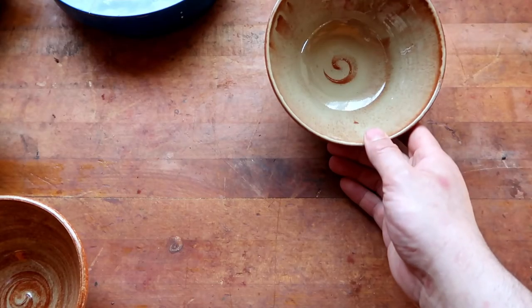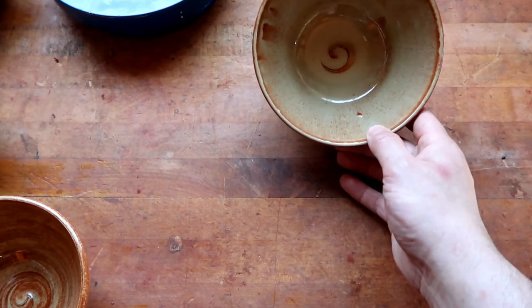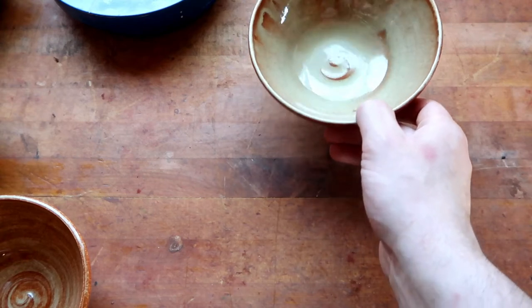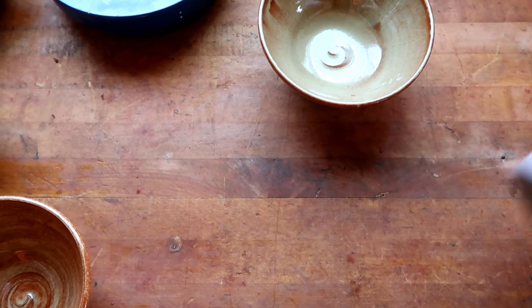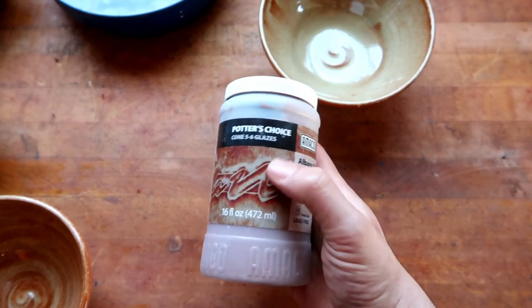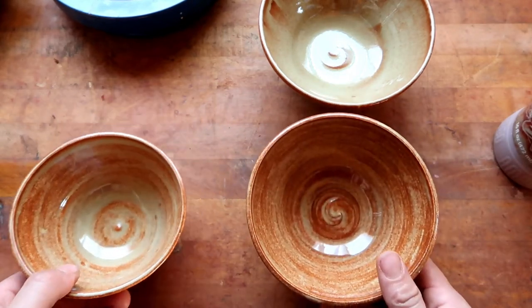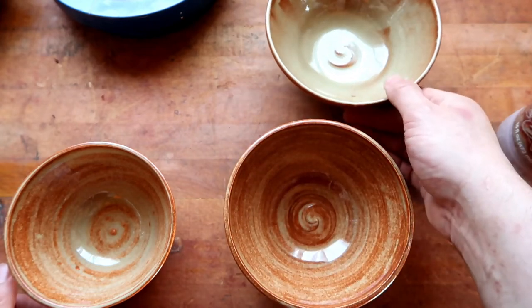And this is kind of weird to say, but this goes with my assumption earlier. There is more white on this because there's a heavier coat of glaze on this. So I think it's safe to say at this point, especially with me pouring on all the glaze on this one, that the more glaze you put on of Albany Slip Brown, the more white it's going to get. But it doesn't seem like you can just put one coat extra and get more white, right? You're either going to have to go above 4 layers, or you're going to have to pour the entire thing on.